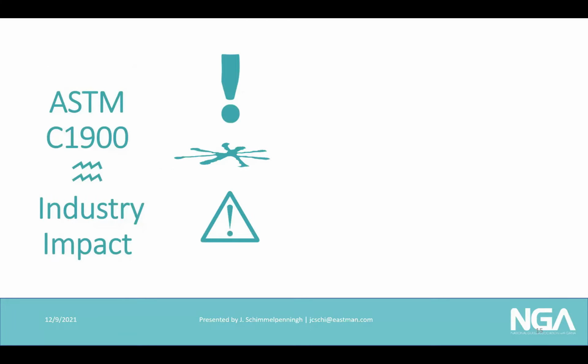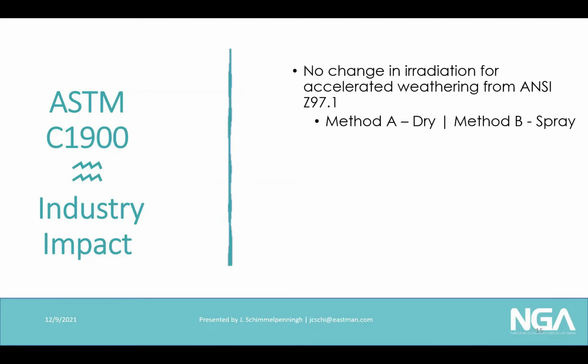So what's the industry impact for the C1900 coming onto the scene? Well, the good part is there's no change in the irradiation for the accelerated weathering for ANSI Z97, and there's no change for natural exposure either. The only difference is C1900 does give you a very concise dry method, where the ANSI Z97 only currently requisitions the spray method, and you have to weather another piece of glass as a control. So that's one change. So the good news for the industry is you don't have to go and redo a whole bunch of accelerated weathering in order to comply to C1900. It standardizes weathering and reporting for materials, so it allows that comparison under the same conditions.